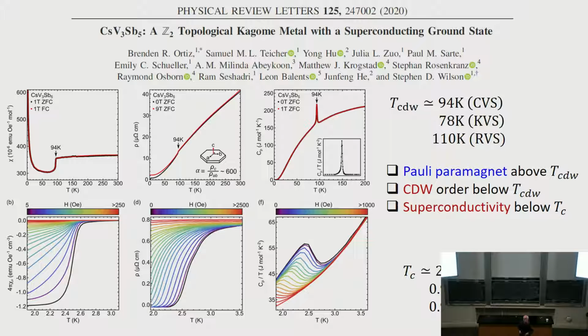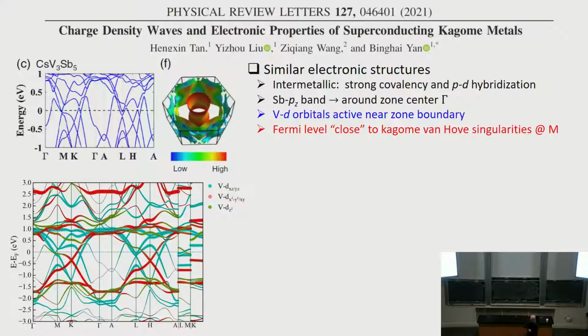Usually what we do is we look at the band structure. We want to ask, is there anything special from these band structures? All 3 materials share the same band structure, very, very close to one another. And if I ask you, does this band structure look like a Kagome lattice? Does it remind you of these 3 bands that I drew for you?